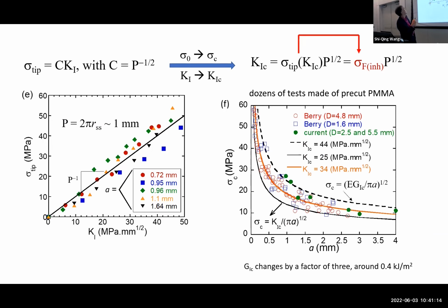Not only that, this relationship works all the way to the point of fracture. Oh my God, that allows me to say a great deal. In other words, I carry this relationship all the way to the fracture, therefore all the way to Kc, which is the toughness. I realize that is related to the tip stress reaching some limiting value, which we identify as inherent strength. So all of a sudden, Kc not only has this operational definition of the loading and cut size, independently, I have Kc related to the inherent strength of your material and a characteristic length scale.